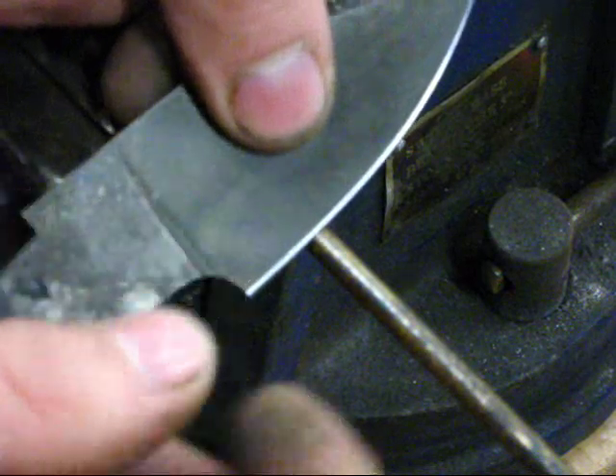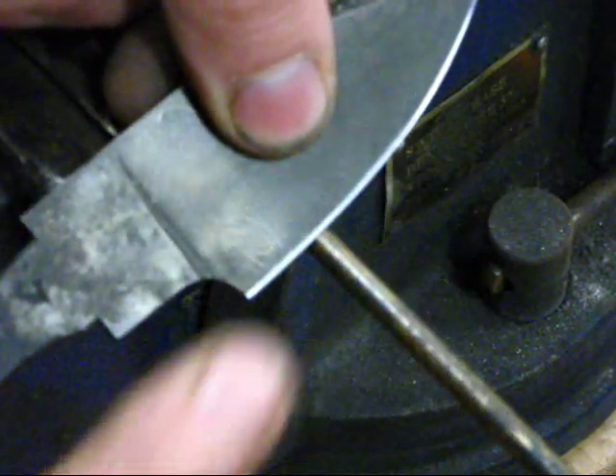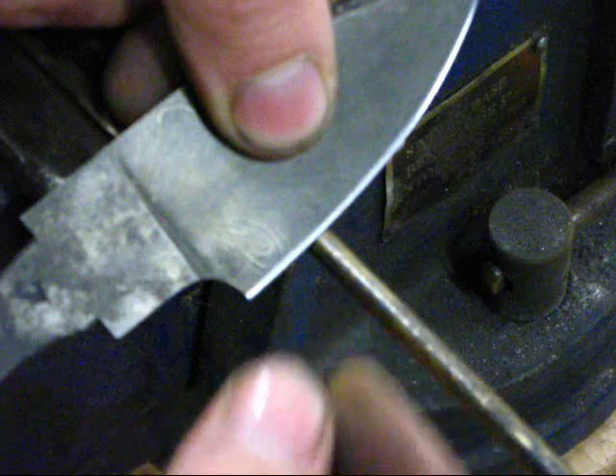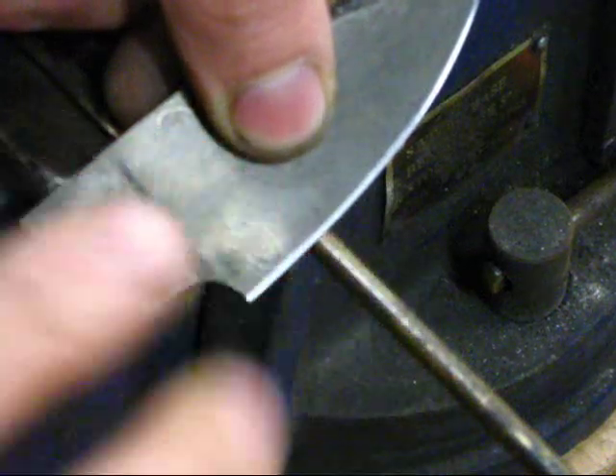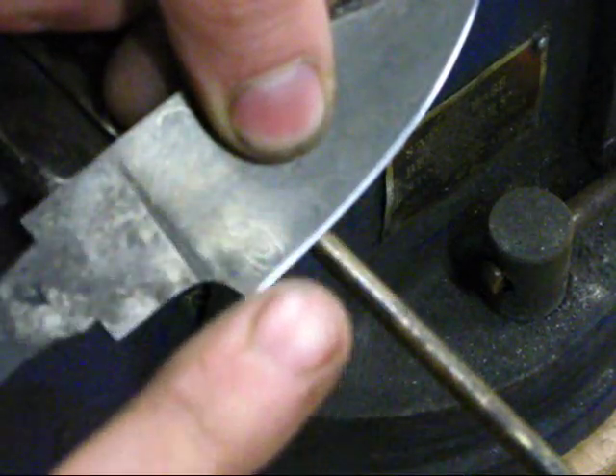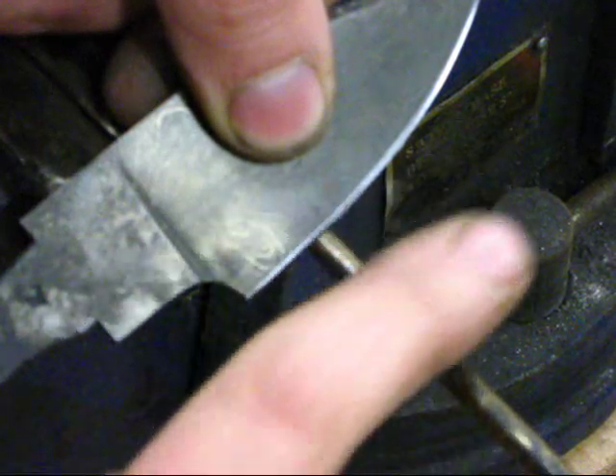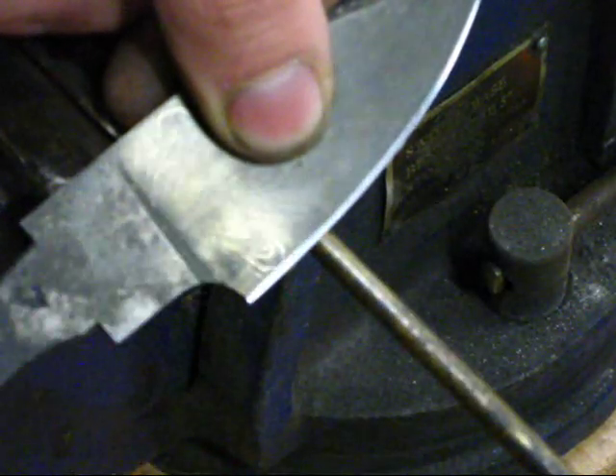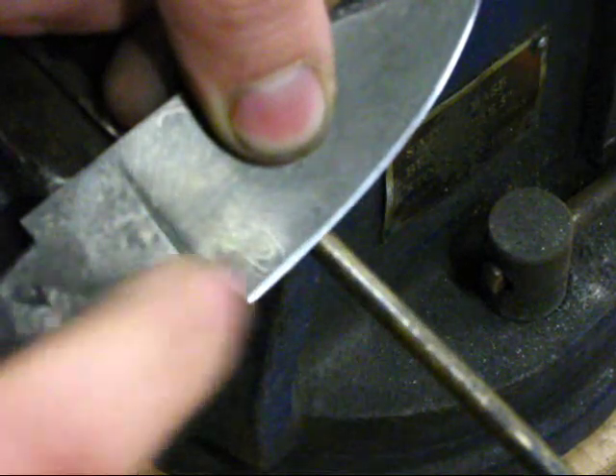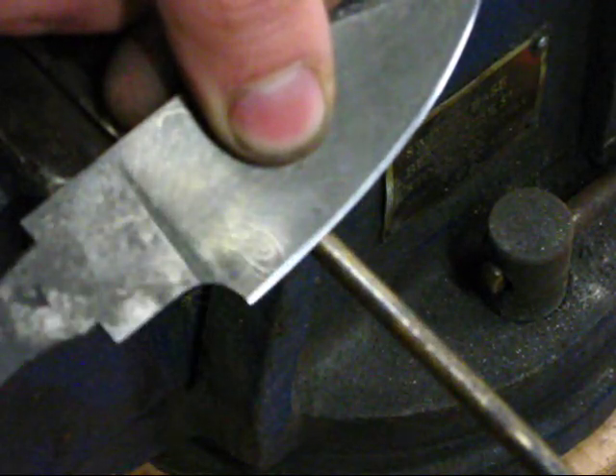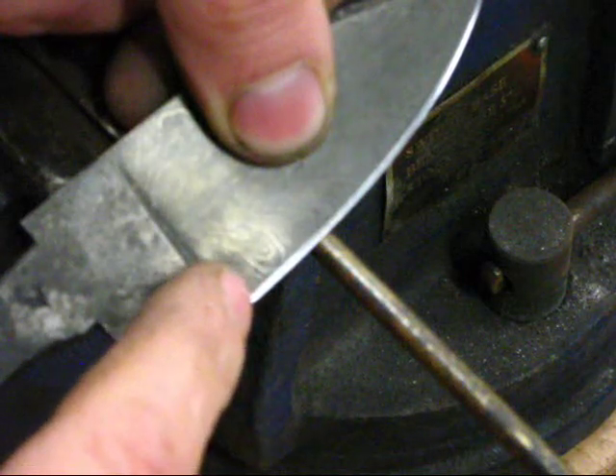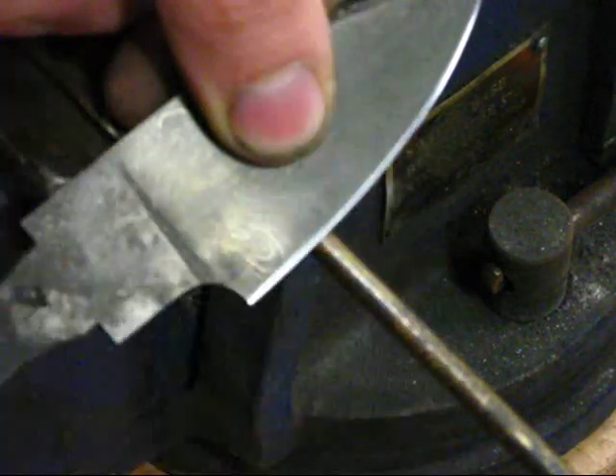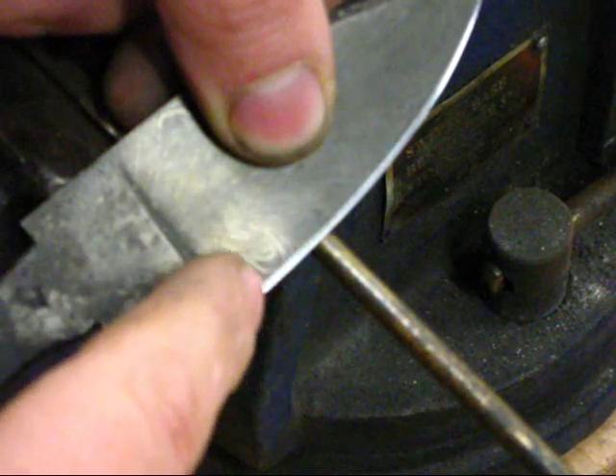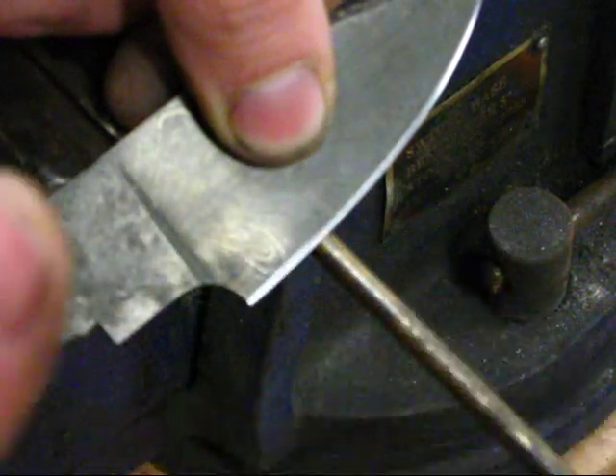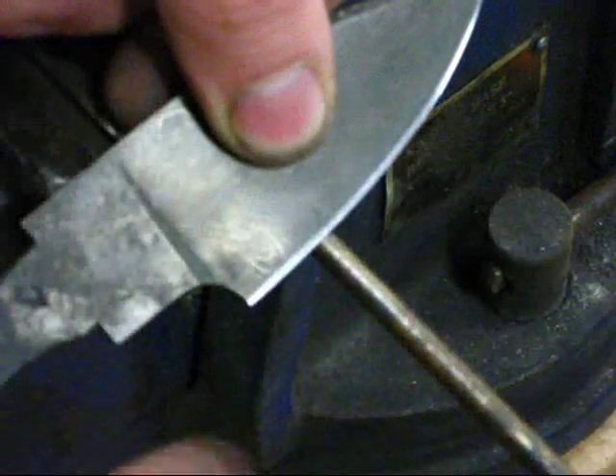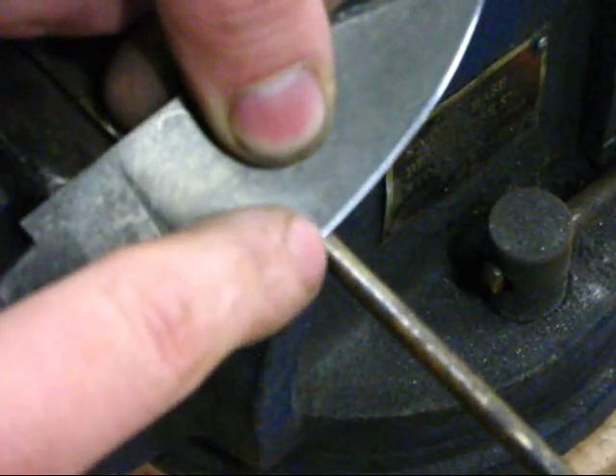And what I am watching for is I actually want to see the edge flex around this brass rod. It may not show up in the camera, but if you do this in person, you'll be able to see the edge deform and flex around this brass rod. If the edge doesn't deform and it actually chips out, that means that this steel is too hard in this edge, and the edge is too hard for a good usable knife. And what that means is I need to take the knife and put it back in the tempering oven, turn the temperature up, say 10, 15, 20 degrees, temper for another temper cycle, and then do the edge flex test again.